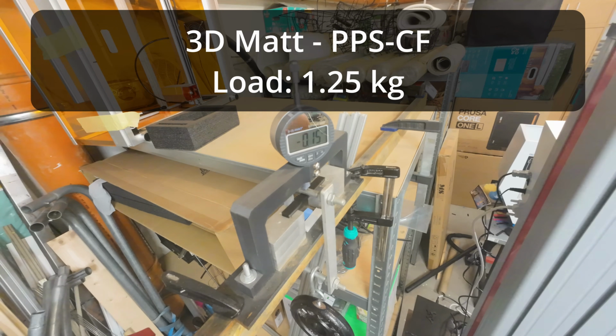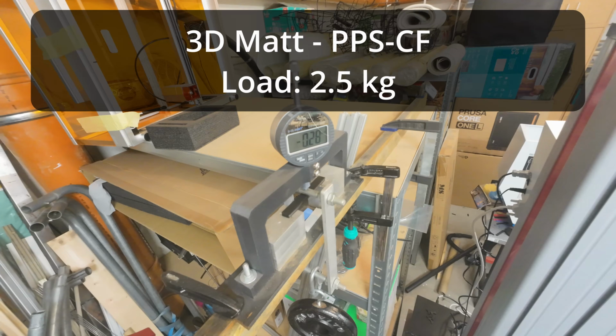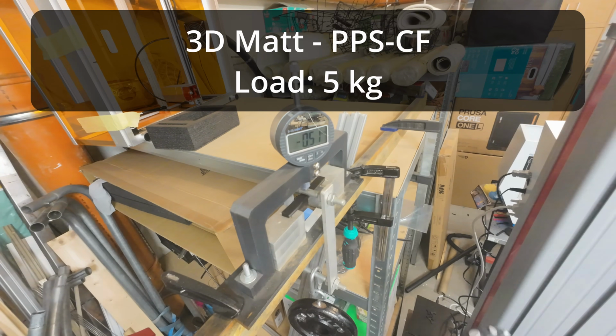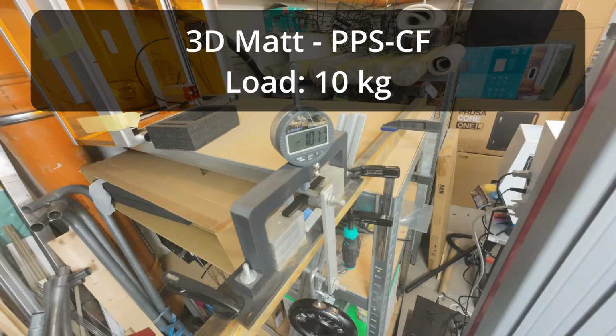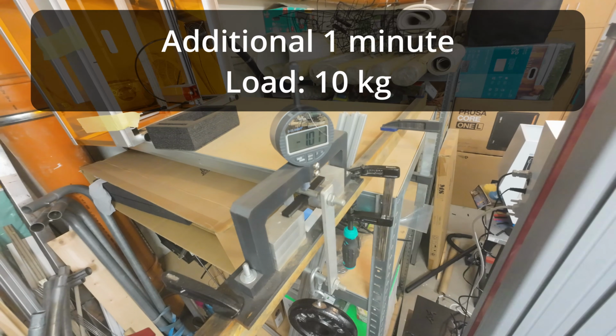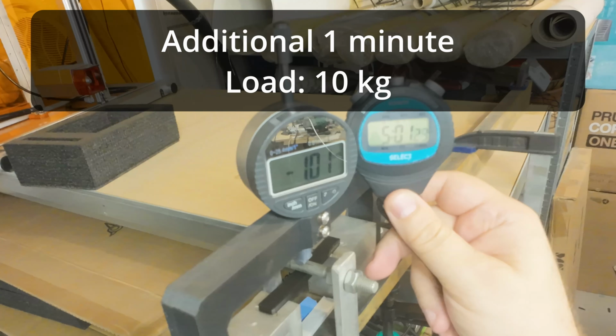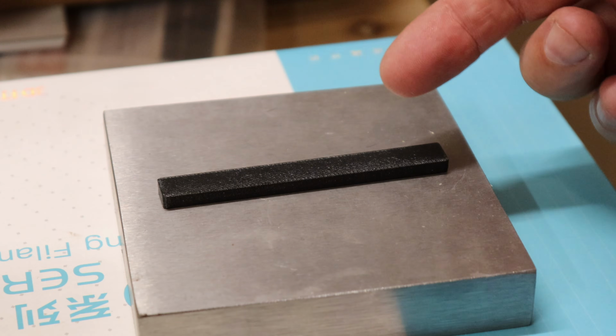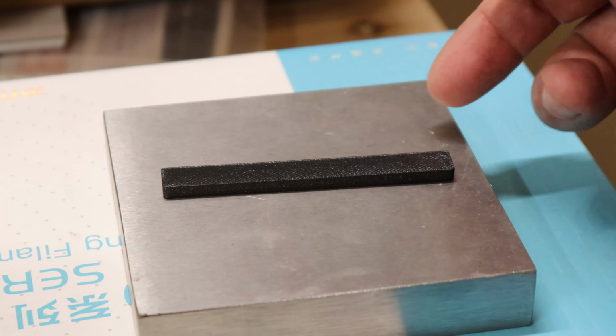Another 3-point bending test. Distance between supports is 50 millimeters, and I am placing these loads one by one every 1 minute, and I am measuring the deformation after 1, 30 and 60 seconds. Currently this is under 10 kilograms, and usually I end the test here, but this is an additional 1 minute, and you can see absolutely no changes. And visually no permanent deformation after this test.